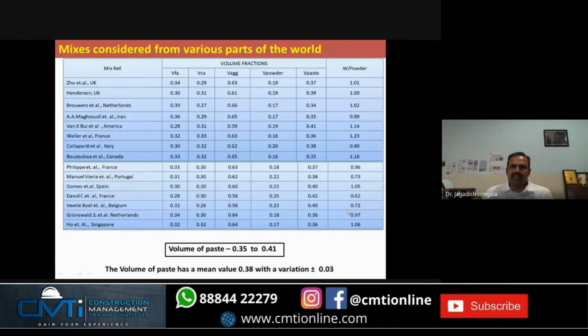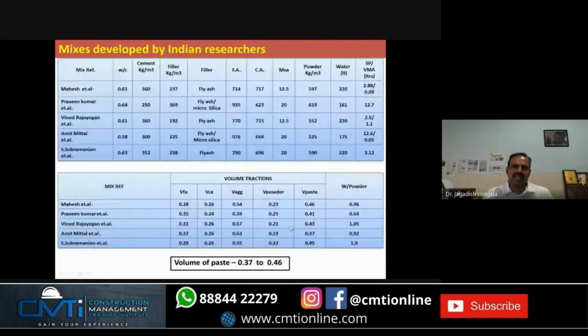In normal concrete, the volume of paste is around 23 to 29%. But in case of SCC, you can see here 35 to 41%. More paste is required in case of SCC. So we have come to a conclusion, particularly for all over the world, the volume of paste is generally between 0.35 to 0.41. But when it comes to the Indian researchers, Indian cases, you can see the paste content is between 0.37 to 0.46. We need more paste because we don't get graded aggregates, so we require more paste due to various reasons.